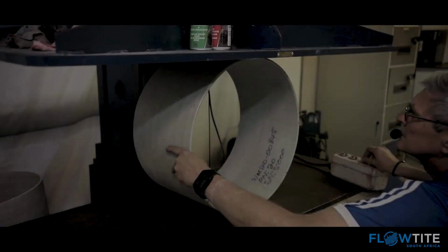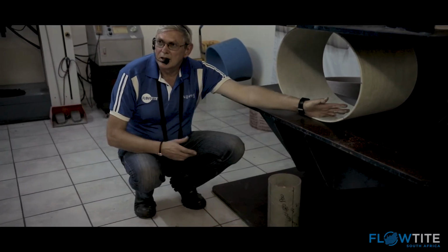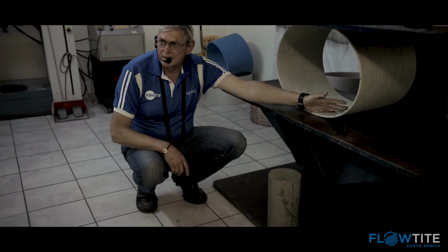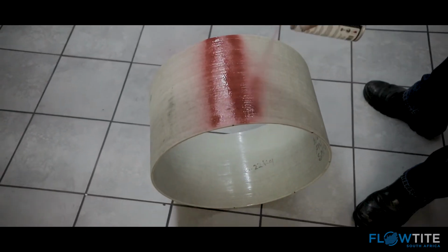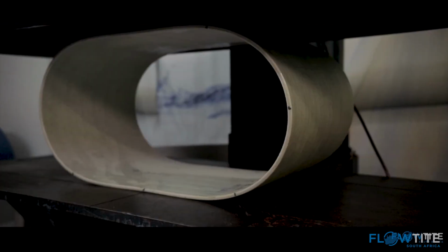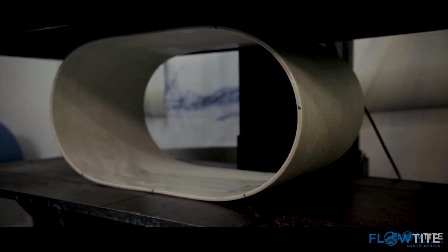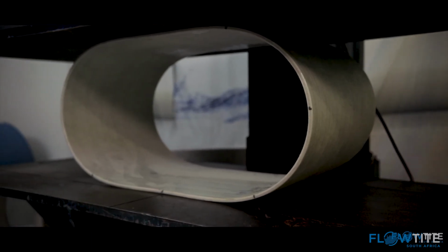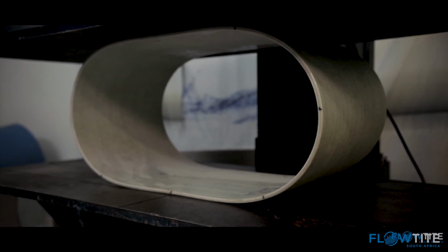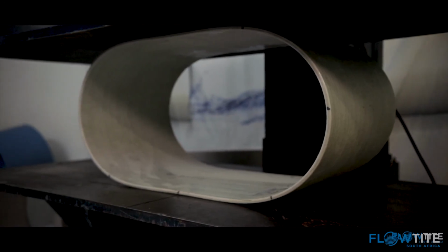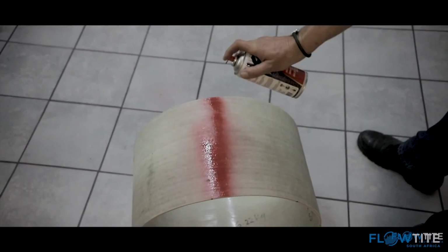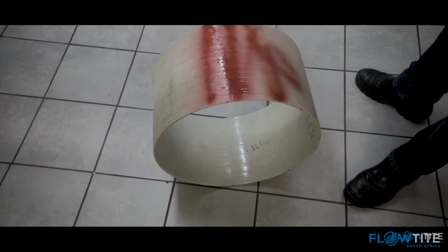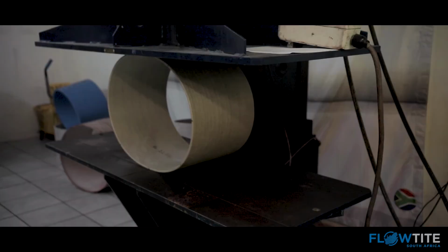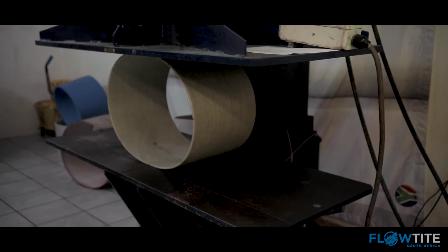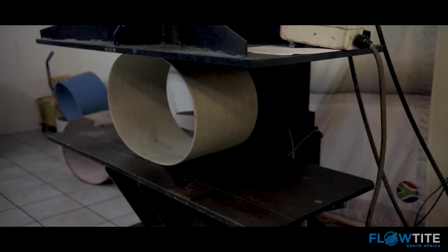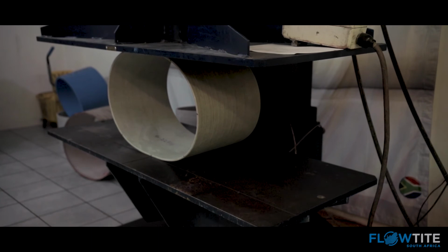Lastly, we test the deflection of the pipe. We place the pipe under pressure from the top and bottom of the pipe until it reaches a maximum of 20% deflection of the original diameter. This is being tested at 2 mm per minute. The pipe is then sprayed with a penetrating dye to see if there are any visible cracks and breaks in the lining. The original design specification allows for no separation or cracks within the layers.